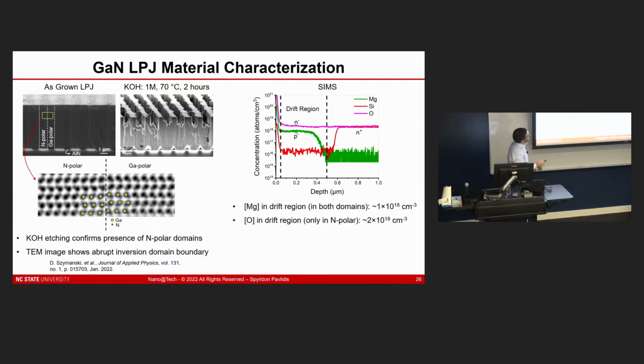And then we wanted to think about charge balance or impurity incorporation. And so we did a SIMS scan here to look at depth analysis, and we tracked magnesium through this structure. You can see that there's a 1E18 level. And keep in mind that when we're sampling the SIMS here, we're doing it across a large area, so it's capturing impurities in both the nitrogen polar GaN regions and the gallium polar GaN regions. So we're seeing about 1E18 in these regions.